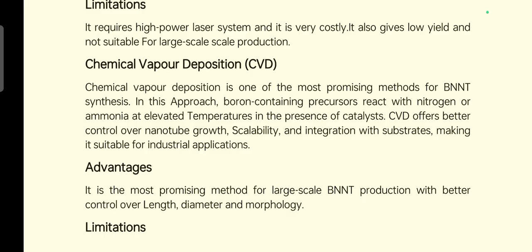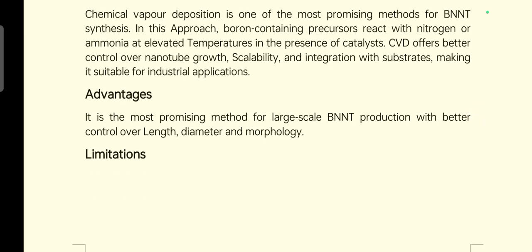Chemical vapor deposition is one of the most promising methods for boron nitride nanotube synthesis. In this approach, boron containing precursors react with nitrogen or ammonia at elevated temperature in the presence of a catalyst. As a catalyst is present in this system, CVD offers better control over nanotube growth, scalability, and integration with substrate, making it suitable for industrial applications. Here are also some advantages of this process. It is the most promising method for large scale boron nitride nanotubes production with better control over length, diameter, and morphology. Thus, we can say that this method is applicable for large scale production.